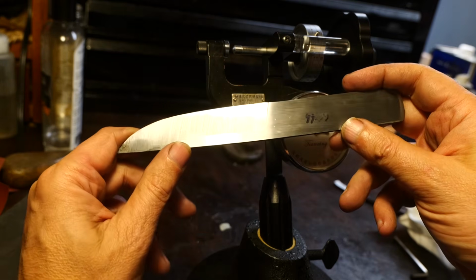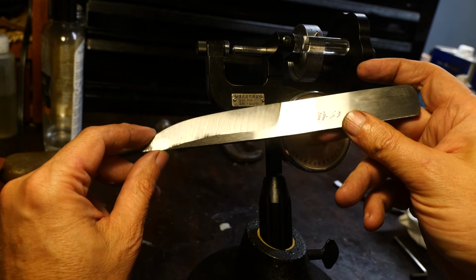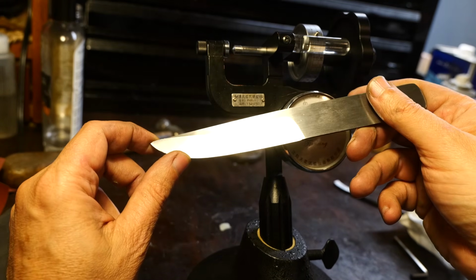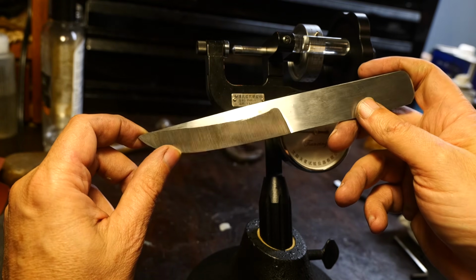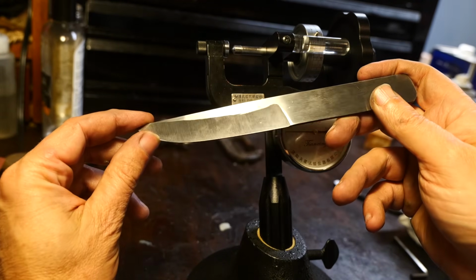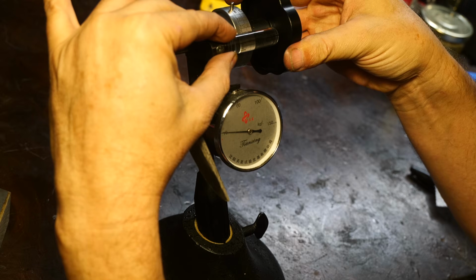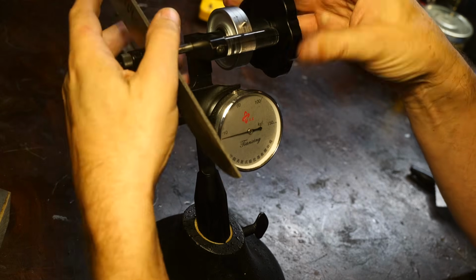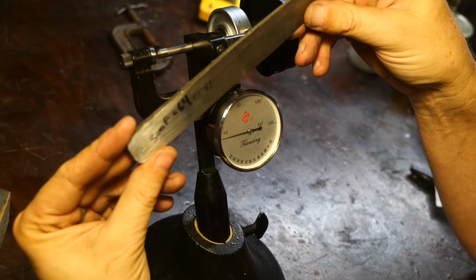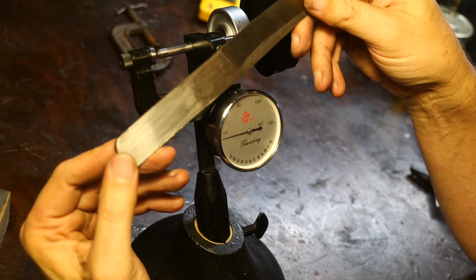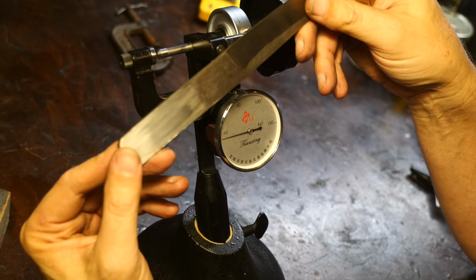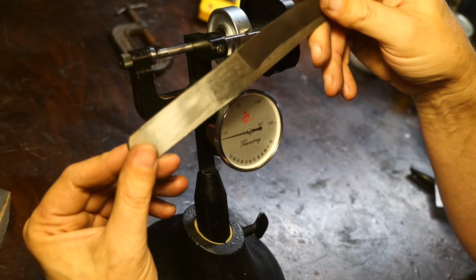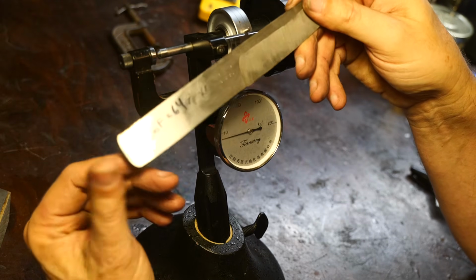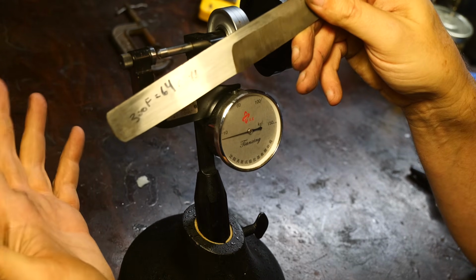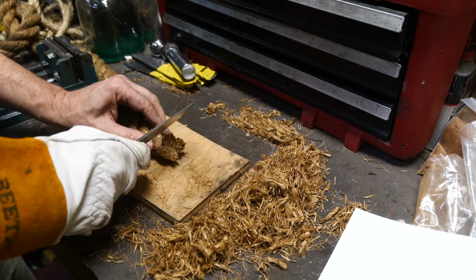I'll go ahead and temper this. We'll get a sort of an initial temper curve. I'm going to try to get it close to 63.5, and we'll retest it through rope and just see if it performs the same from a higher quench temperature. All right, so this was tempered at 310 degrees, and I got a bunch of 63, 63 and a half, 64, and 65 readings. So I'm just going to say that this is 63 and a half roughly, just like it was last time at 310 degrees.